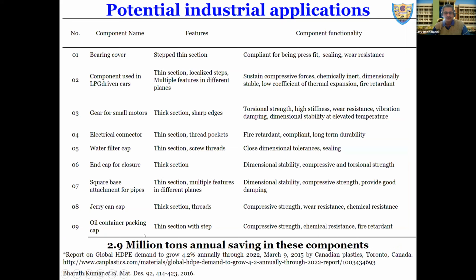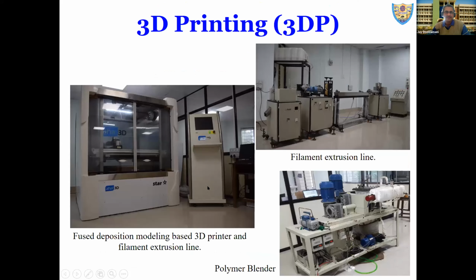And we found out that we can make the foams eco-friendly by having fly ash there in thermoplastics using industrial scale manufacturing. Recently, from the last 3 to 4 years, the focus has been shifted to 3D printing, and we have in-house a 3D printer and the filament extrusion line. So we manufacture the filaments in the lab of different compositions and different foam elements, and we print them.